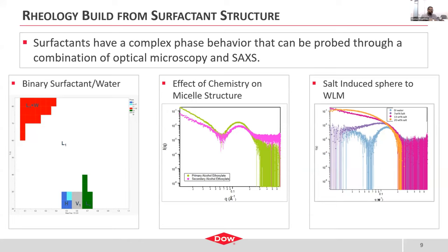Also, when you're in these dilute micelle regimes, which is often where you are when you're dealing with detergents, in the 5 to 9 weight percent regime, you want to build viscosity. You can build viscosity by going into these liquid crystal regimes. However, there you're going to get into the situation where you're going to have to scoop your shampoo out of the bottle with a spoon. So what we often do is change the morphology of the micelles using another variable, like salt or electrolyte concentration.